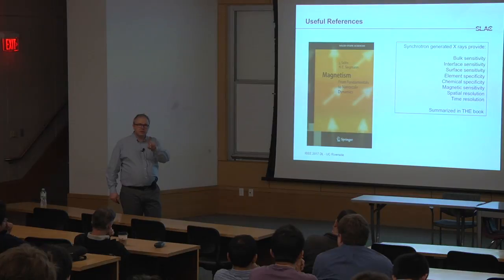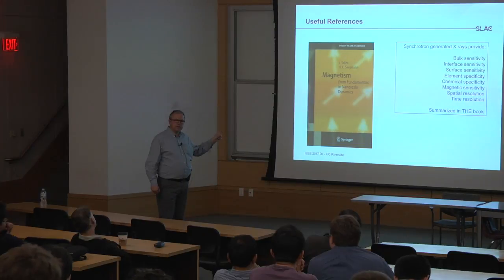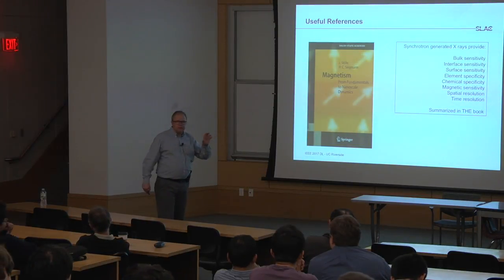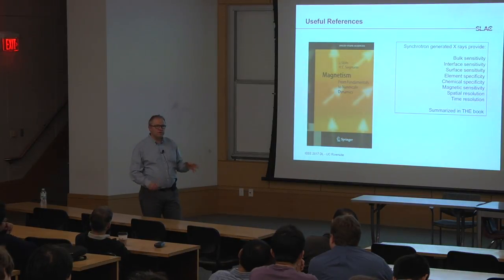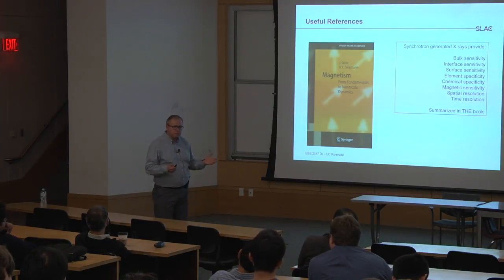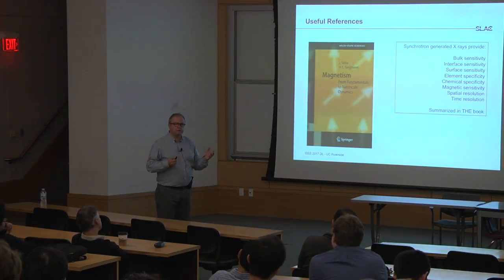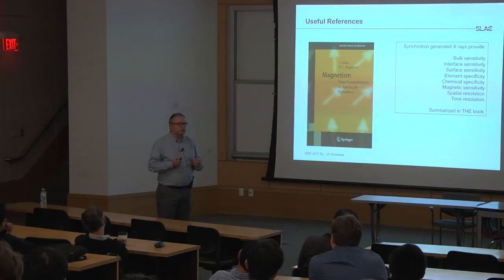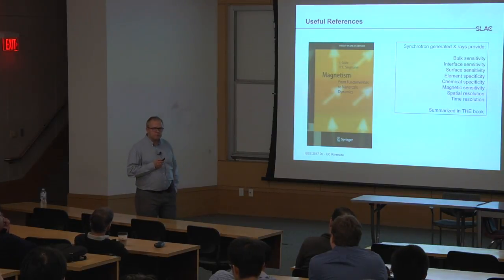The question was that the spin accumulation that we found was much smaller than the one that we actually suspected before, the 10 to the minus 3. The 10 to the minus 3 was also an experimental limit. People have tried with other methods to see whether they could see any evidence of spin accumulation in the non-magnetic layer, and that's pretty much the upper limit that they extracted, because they figured out what their error bars in their experiment are. Although, yes, in general GMR theory, you would expect something of the order of 10 to the minus 3 to 10 to the minus 4.